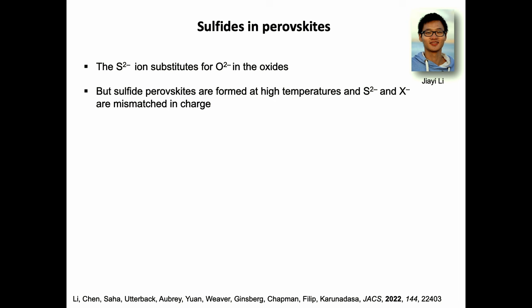Sulfide perovskites are formed in a furnace at 1,000 degrees. Halide perovskites form at room temperature in water. So these are highly incompatible synthetic requirements. Second, sulfide has a 2- charge, and halide has a 1- charge. And we cannot simply expect a 2- ion to adopt the same lattice structure as a 1- ion.